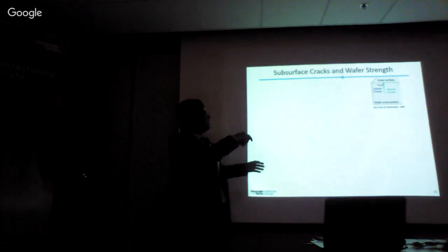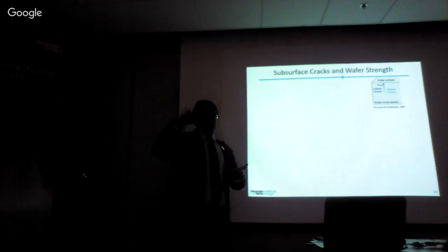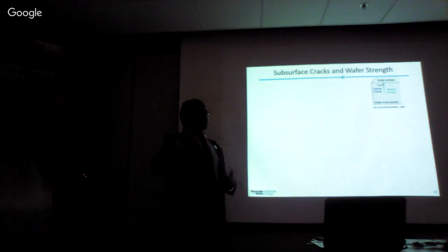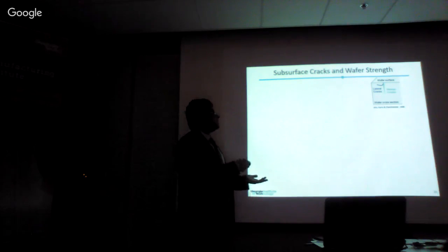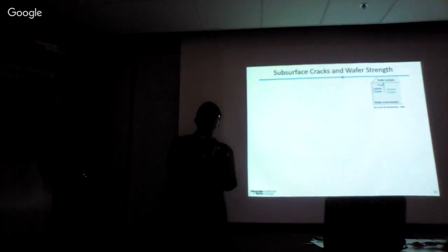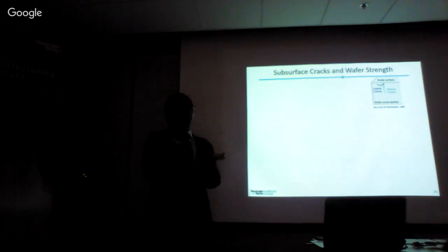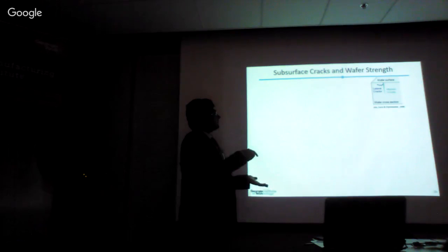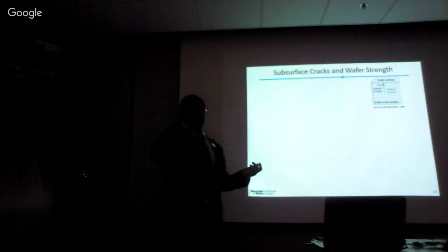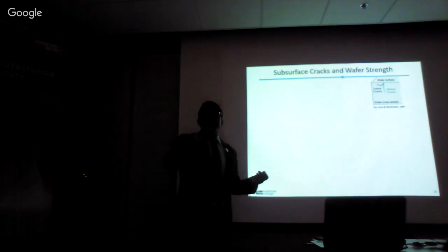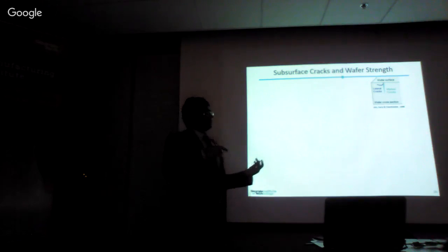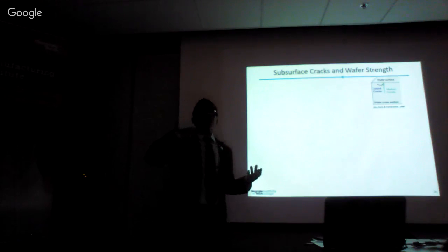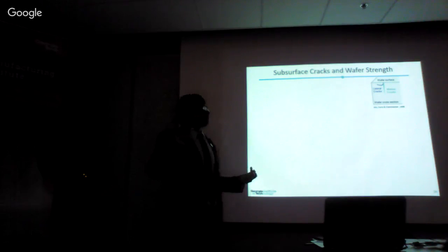Before we go into the results, whenever there is a sliding of an indenter, like a diamond indenter, on a brittle material like silicon or glass, two types of cracks form. The median cracks, which are perpendicular to the surface, and they cause fracture in crack opening mode, or mode 1 of fracture. And lateral cracks, which start from the bottom of the groove and then go upwards, and if they reach the surface, they chip out. So these are the two types of cracks being formed, apart from radial and chevron cracks, which we saw in task 1, formed during scribing with differently shaped abrasives.